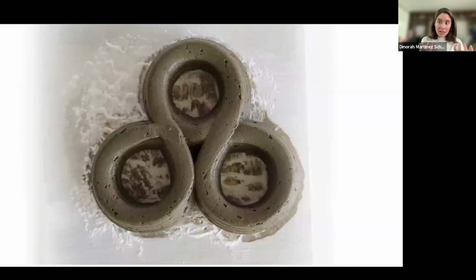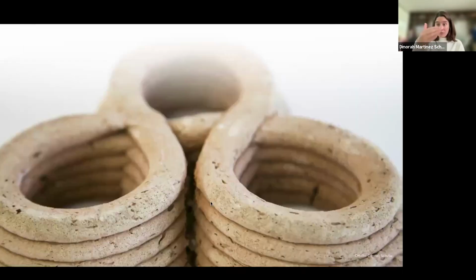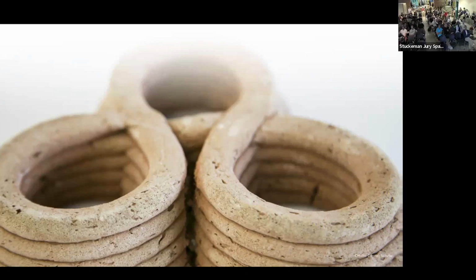It's a foam. It's mineral foam, like the soap foam that we use every day to wash our hands. This is the same. And you can also see the porosity in the holes that the material is producing in the whole geometry. Then after the firing process, we have this color. It looks like clay, but it's not clay. One of the benefits of using foam instead of clay is that you have a very low density. So all the elements are very lightweight.